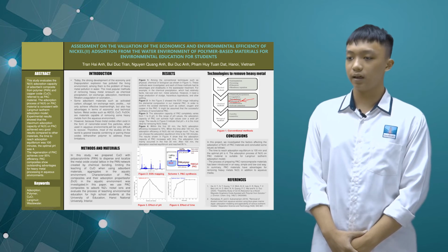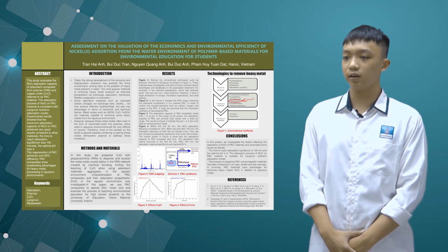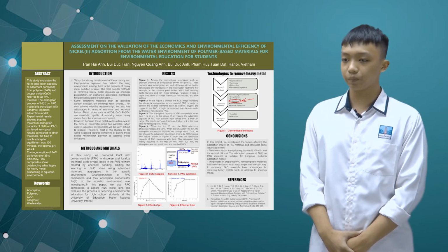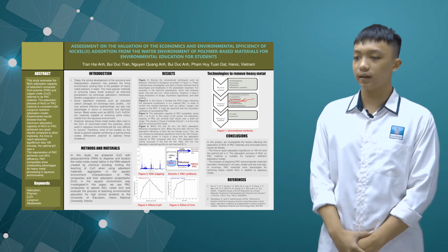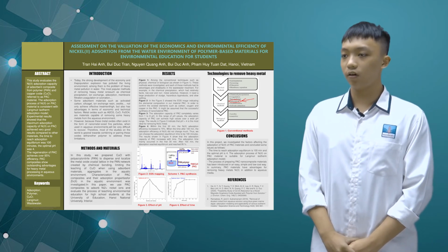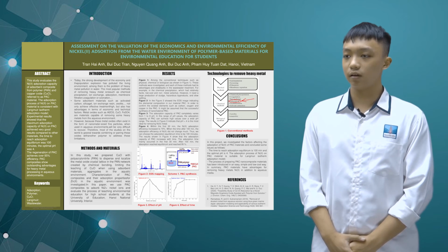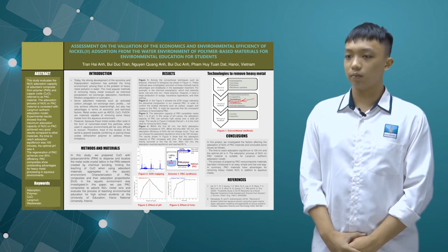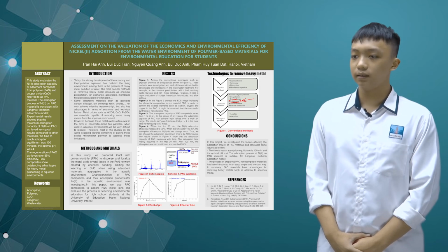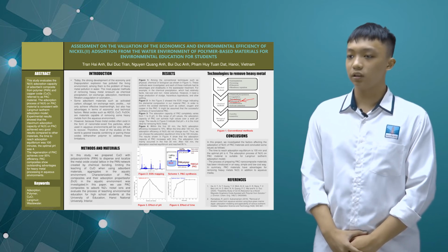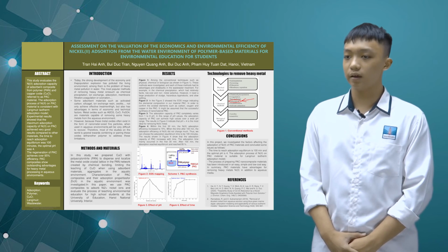The optimal pH was discovered in our experiment after testing pH values ranging from 1 to 8. As shown in figure 3, pH 4 is the most effective for nickel removal. Lastly, figure 4 demonstrates that the adsorption capacity of PAC increased with time. The adsorption mainly occurred in the first 30 minutes. After 100 minutes, the adsorption reached 95%, which is equilibrium.